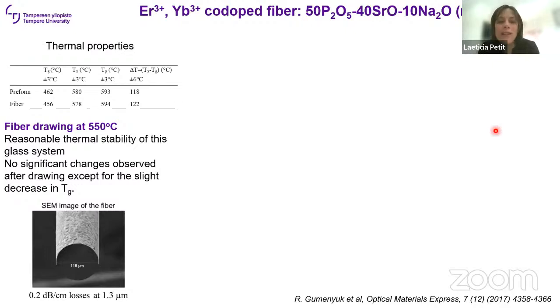Back in 2017, we made the first erbium, ytterbium co-doped phosphate glass fiber. We were able to draw fiber using a drawing temperature of 550 degrees C. And here is the SEM image of the fiber. We measured losses of 0.2 dB per centimeter at 1.3 microns. Our goal was not to reduce the losses as much as we could, it was just to prove that we could draw this composition into fibers.